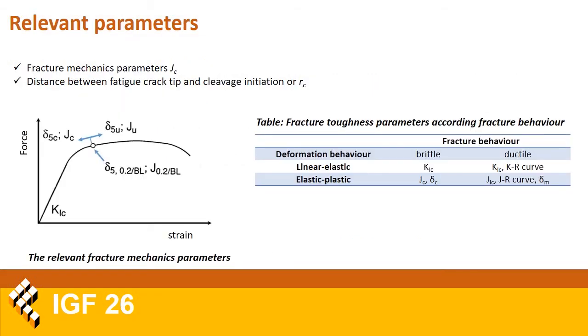According to material properties, obtained values of the strain diagram and the matrix shown on the slide, the relevant fracture mechanics parameter obtained by testing of the previously mentioned CT50 specimens was the J integral at the moment of a cleavage fracture, or just simply JC.